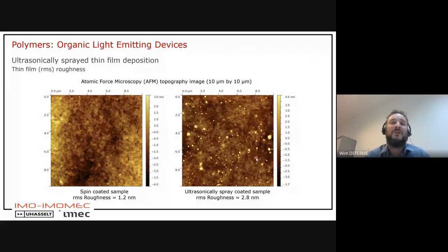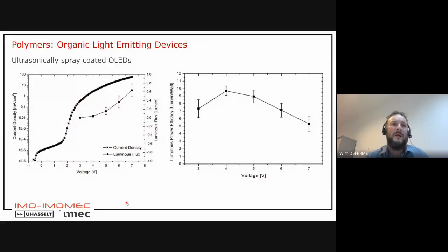Finally, we optimized the parameters for spray coating, and we look at atomic force microscopy. Here you see an ultrasonic spray coated sample having a thickness of 80 nanometers, with a roughness around 2.8 nanometers, while if you compare it with a spin coated one on the left side, you see a roughness around 1.2 nanometers. So roughness wise, it seems to be okay. It's not perfectly the same as spin coating, but it's quite okay. If you think about 80 nanometers, 2.8 nanometers is quite okay.